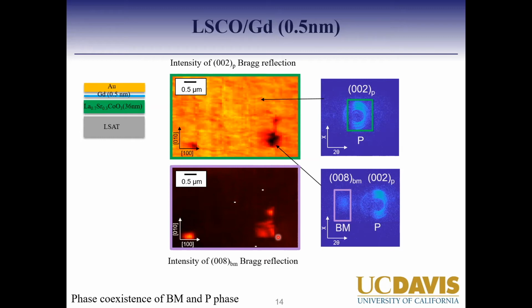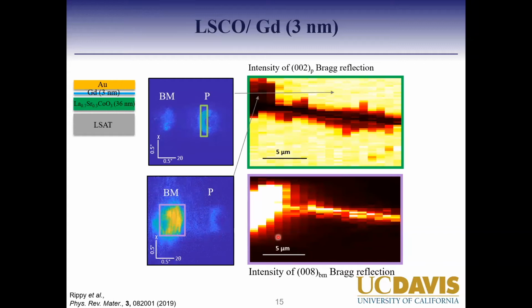We can change the gadolinium thickness and measure a different sample. This is the gadolinium 3 nanometer sample, measured in exactly the same manner. Here we start to see the formation of some interesting filaments in the material and very strong conversion to the brownmillerite phase. Again, you have the nice perovskite peak, giving you this yellow-white contrast in these regions, and there is some brownmillerite present in this region. If you look at these dark regions, that's where you see intense brownmillerite peaks, and if you integrate that over, you can see the reversal of the contrast. So indeed, as you move to gadolinium 3 nanometers, instead of a distribution like blobs, you start to move towards formation of filaments in the system. So that's one key takeaway.